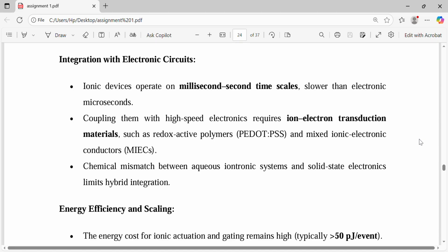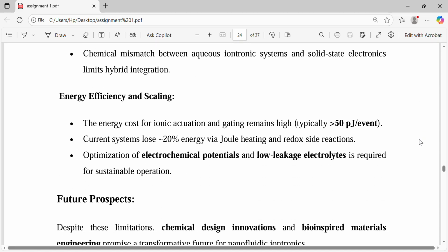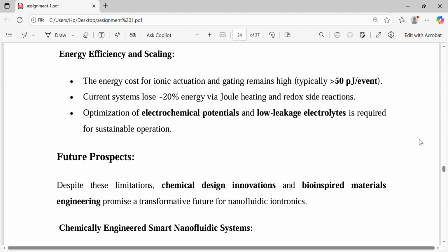Coupling them with high-speed electronics requires ion-electron transduction materials such as redox active polymers and mixed ionic electronic conductors. Chemical mismatch between aqueous iontronic systems and solid-state electronics limits hybrid integration, energy efficiency, and scaling. The energy cost for ionic actuation and gating remains high, typically greater than 50 pJ per event. Current systems lose 20% energy via Joule heating and redox side reactions. Optimization of electrochemical potentials and low leakage electrolytes is required for sustainable operation.